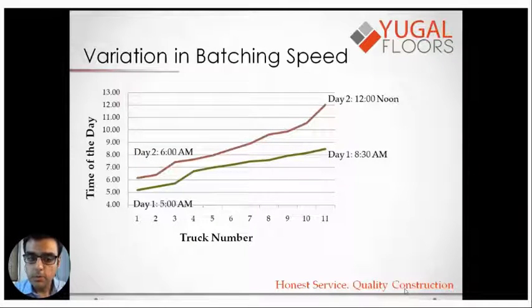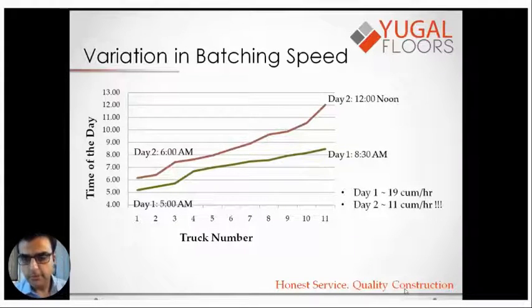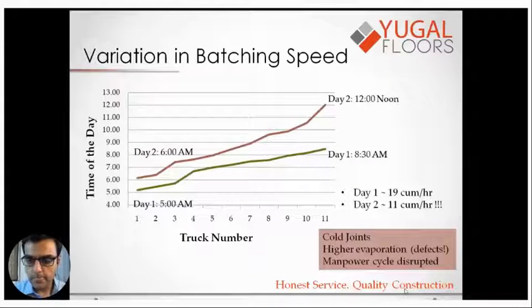It went up till 12 noon. So what implications does this have on me as a flooring contractor? First thing I would like to highlight here is, the average concrete speed on day one was 19 cubic meters per hour. Day two was 11 cubic meters per hour. It's almost half. So the risk that I am running is cold joints, higher evaporation because 12 noon is much hotter than 8:30 a.m., and my manpower cycle is disrupted.